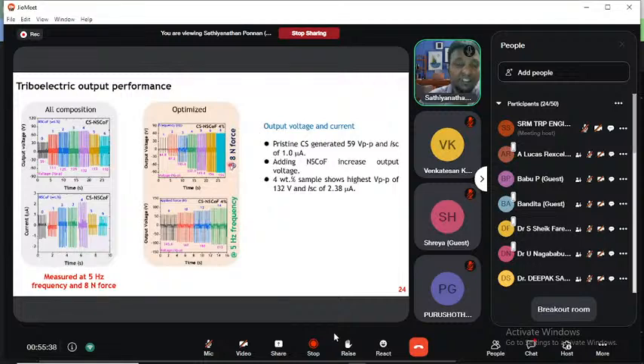As expected, when you increase the force, the performance will increase. That is an already proven effect, and we also observed this similar thing in our system. When we increase the force, the output keeps increasing, up to 132 volts at 8 Newton force. Similarly, at a frequency of 9 hertz it shows 145 volts. When we increase the frequency up to 14 hertz, the output voltage increases up to 212 volts.